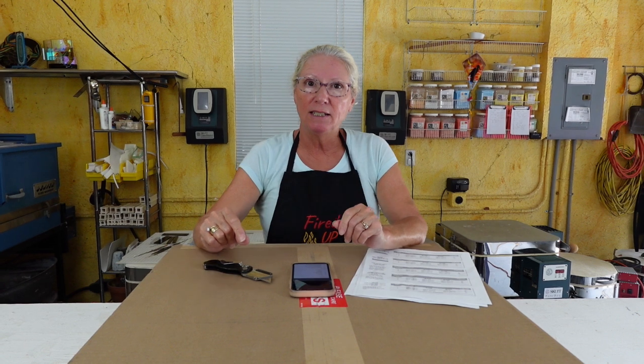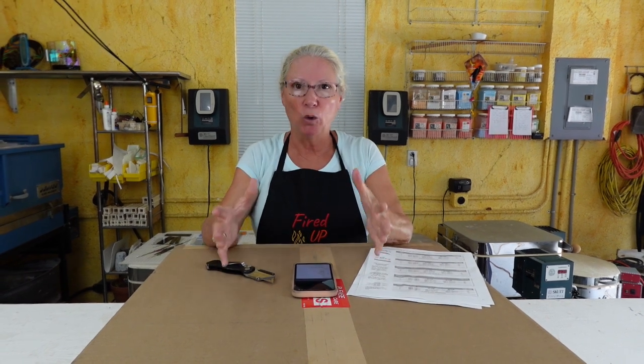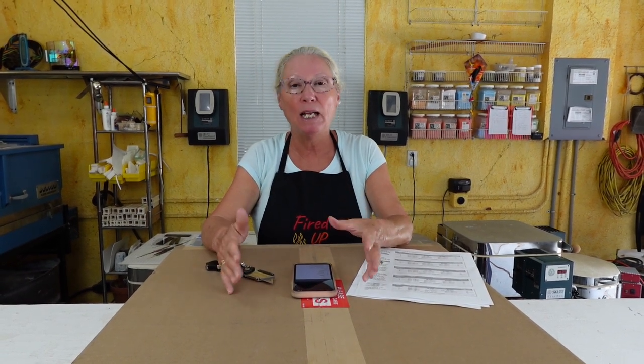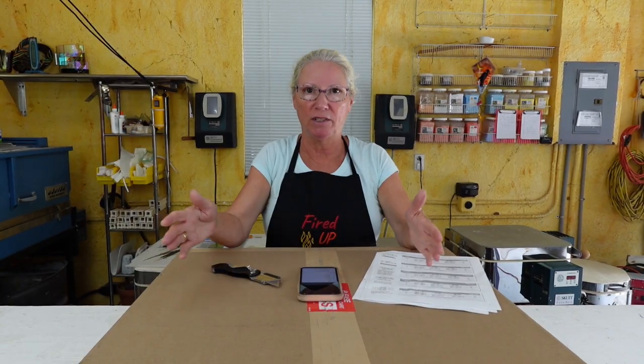What the hold does is it allows the glass to absorb that temperature, react to the heat, and make a change. The change we're looking for at full fuse is all the pieces are melted together, but not held at that temperature so long that it distorts, that we lose the exterior shape, that we lose the thickness. We want consistent results. So that 10 minutes gives us the results we want without overcooking something. If you go less time, you'll have a harder firing, not as soft a surface.